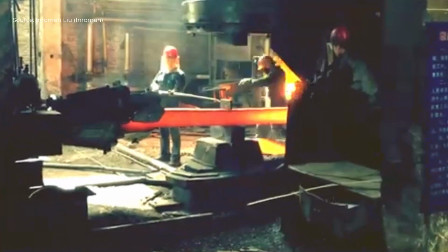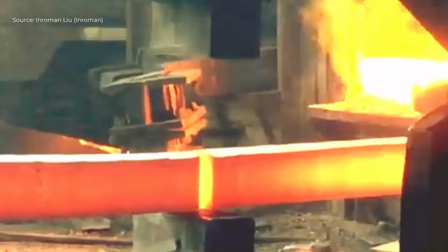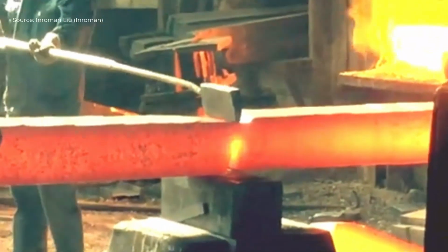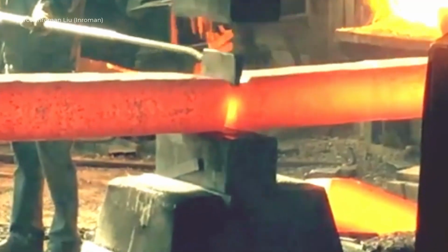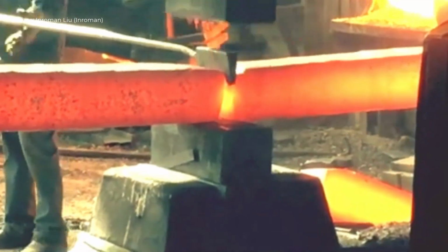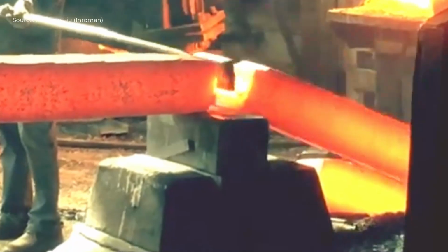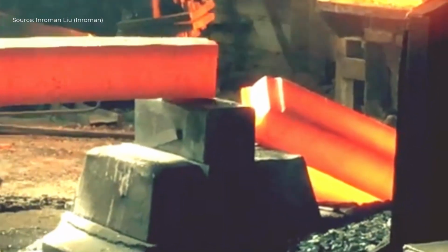After the final forging operation, the part is slowly cooled under controlled conditions to minimize residual stresses. The result is a forged turbine blade with enhanced toughness, fatigue resistance, and strength ideal for demanding steam turbine environments.